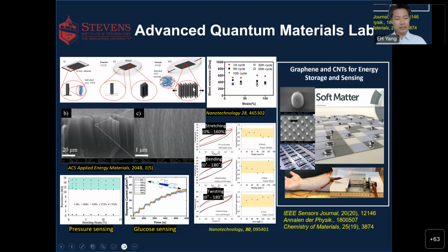And that is proven in this plot on the right. Its y-axis is sheet resistance, which doesn't change over the strain applied to the substrate. This is the sheet resistance measured through these carbon nanotubes. That means there's no change. That means these carbon nanotubes can be used as electrodes, sensing materials, and others, while the substrate is stretched or distorted. So this is basically a stretchable material that can be used for sensors, energy storage, and others.